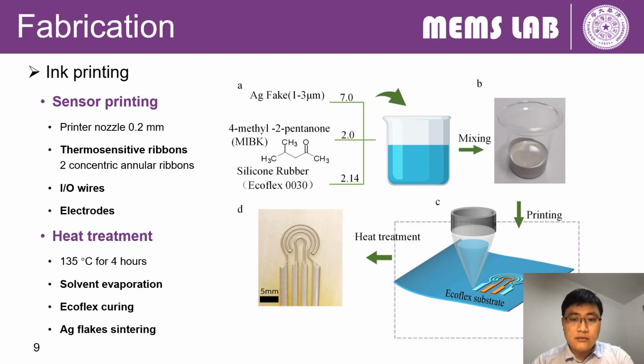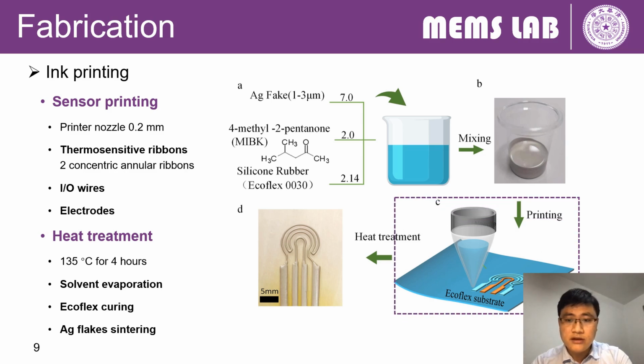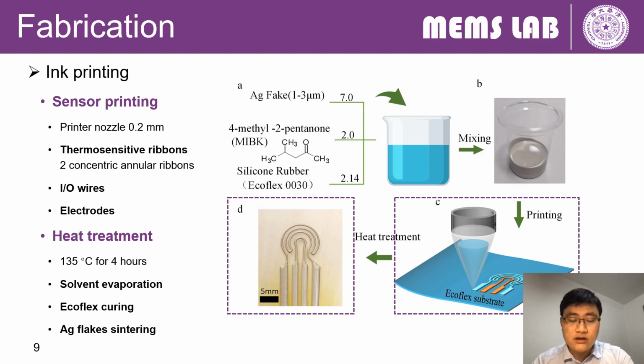The second step is sensor printing. Printing technique is adopted here due to its low cost in manufacturing stretchable electronics with customized designs. Here, the thermosensitive ribbons, wires, and electrodes are formed on the Ecoflex substrate at the same time. Finally, the fabricated sensor is heat treated so as to ensure the evaporation of solvent, curing of Ecoflex, and sintering of the silver flakes.